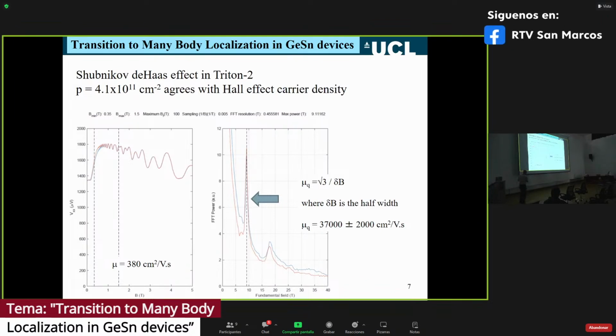If we Fourier transform this data, so these dotted lines here just show the field domain. If we Fourier transform that, as I mentioned on Monday, these oscillations are periodic in 1 over field. So if we plot the Fourier transform of this data as a function of fundamental field, we see extremely sharp lines in the Fourier transform. And as I mentioned on Monday, we can determine the quantum lifetime or quantum mobility or single particle lifetime from this data just from the width of this peak.